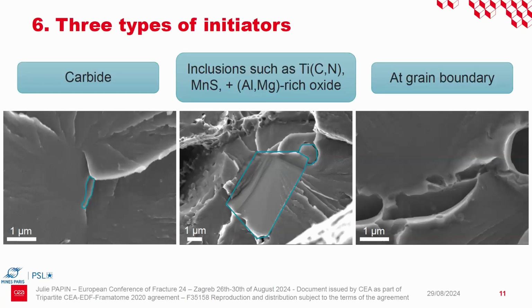Now, after all the fracture toughness tests, we carried out a fractographic analysis of the broken specimens, and we were looking for the initiation site, and we classify these in 3 types. First is the initiation on a carbide, at a grain boundary. The second type is inclusion, often a cluster of inclusions, such as the titanium carbonitride in the big part, and then a cluster with the magnesium sulfide here and here. And sometimes we can find oxides rich in aluminum and magnesium. And the third type is initiation at a grain boundary, but with no visible particle.